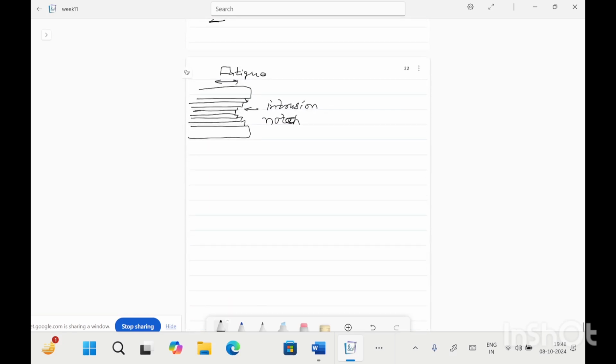If the condition is different, a intrusion or extrusion can also form in this manner. So this is the extrusion of slip bands, or ridge formation, due to the cyclic loading and unloading.